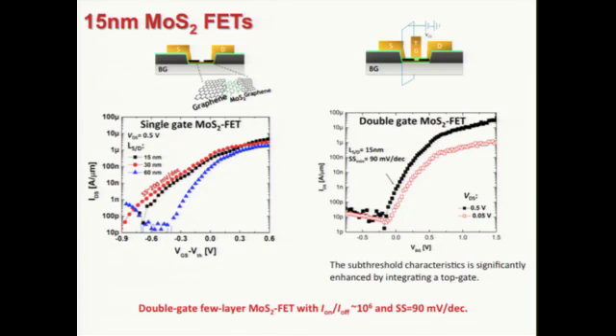So we put down the top gate and connect it to the back gate so that this device now is operating in the dual gate configuration. And as you see, the subthreshold region is much steeper, and the swing has decreased to about 90 millivolt per decade. Here, the off current also decreased to 10 picoampere per micrometer, and we have some improvement in the on current. That's a good device, but as I said, the idea here is to go really down to 10 nanometer and eventually to sub 10 nanometer region.